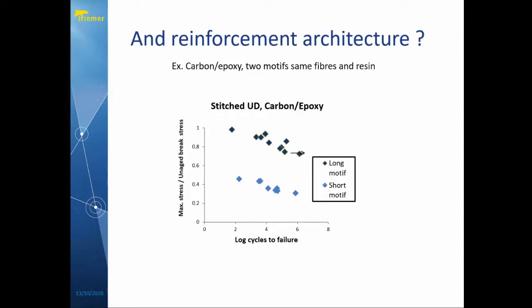So we looked at other materials, and we looked at a much longer motif, the repeat element, and we got this curve at the top here, which was virtually the same as the curve we were getting for the pre-preg material. So you can get very good performance with carbon reinforcements, but again, you do need to be careful about selecting them to optimize fatigue performance.